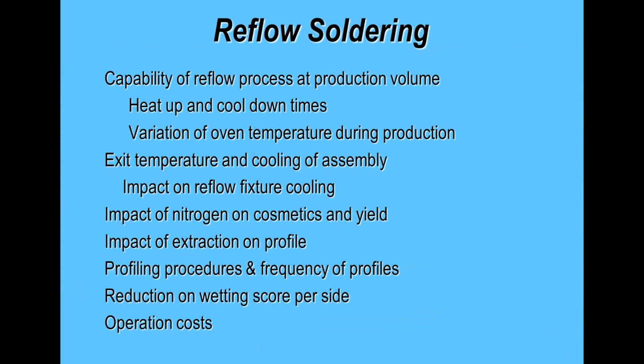Variations of temperature during production are key, and that's why we do profiling. It's also why we do process monitoring profiling, and I say that because that's slightly different. We're looking at how the machine fluctuates as opposed to the temperatures on a board. Now, obviously, temperatures on the board will fluctuate due to machine variation, but that's only something you can do by monitoring the process. And I would say monitoring product within the process or running through the process rather than just the machine settings. You've got to understand the capability of your machine. Also, consider nitrogen if you're going to be running it, and the impact on yield and performance against cost.